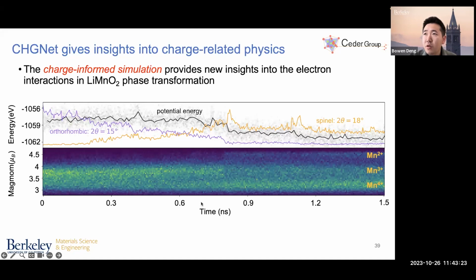And following this major phase transformation point, the manganese 3+ ions undergo a charge disproportionation reaction, resulting in the coexistence of manganese 2, 3, and 4 in a transformed spinel-like structure. And this result indicates the lithium manganese phase transformation is highly correlated with charge transfer. And the formation of manganese 2+ ions in the charge disproportionation reaction only happens in the long time scale of around 1 nanosecond, which is really impossible to simulate using any previous methods.